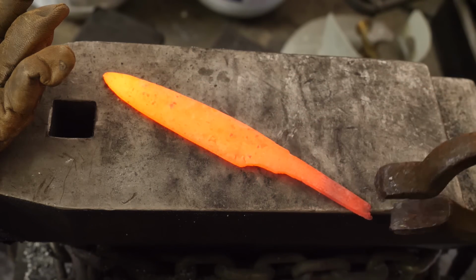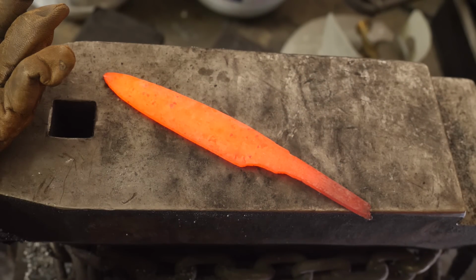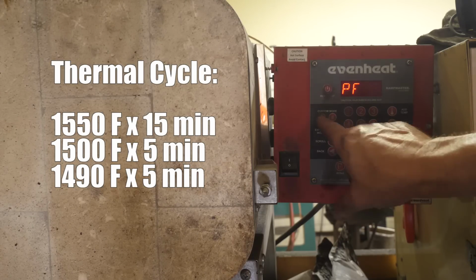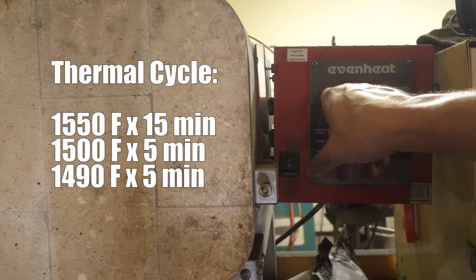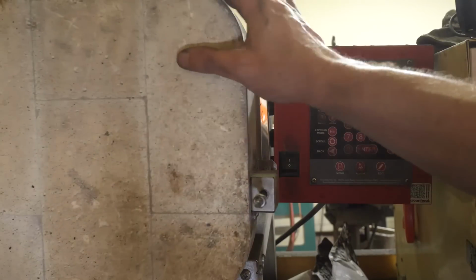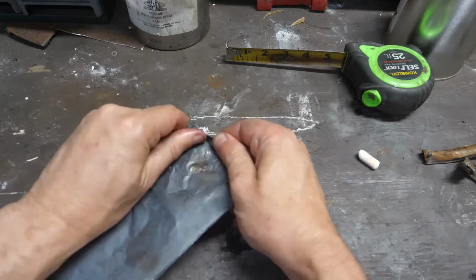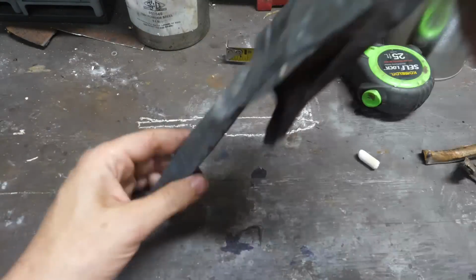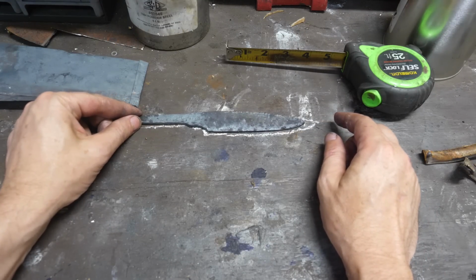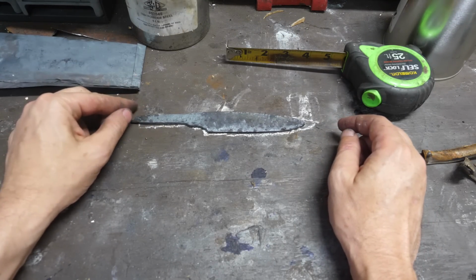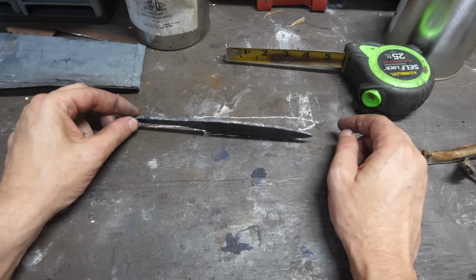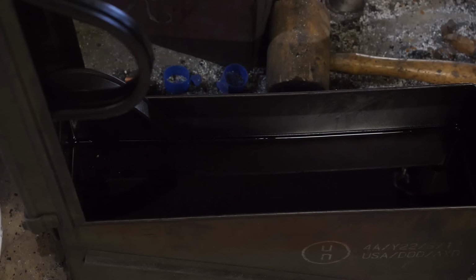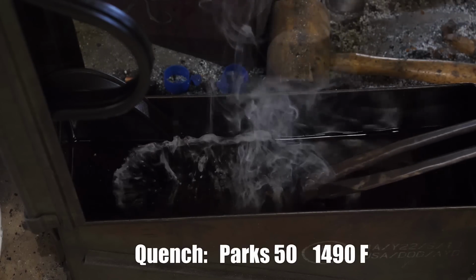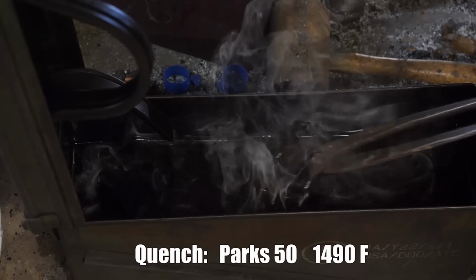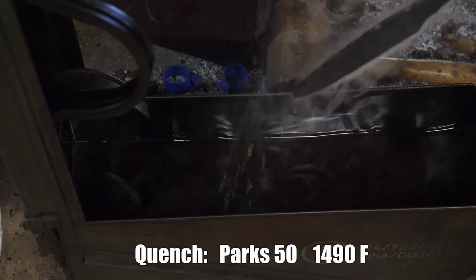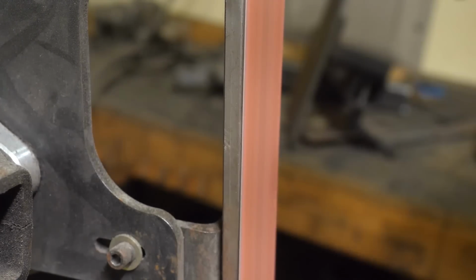So we're going to normalize this 3 times. We're going to start at 1550 in case it is like a 0.5% hypoeutectoid steel. And then we'll just go down to 1490 in case it is just an alloyed high carbon steel. And we'll just cover all our bases there. We should get decent normalization out of that. A little shy on our size goal. Let's get it quenched in the Parks 50 from 1490 degrees Fahrenheit. And then we'll grind it and put a handle on it.